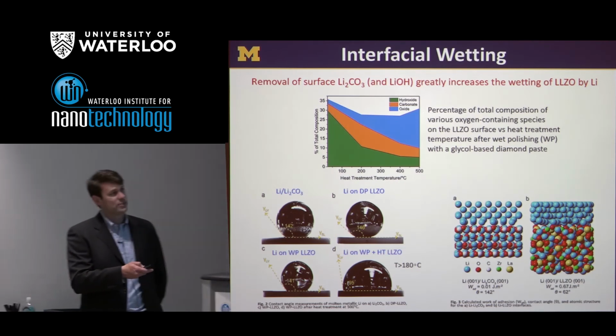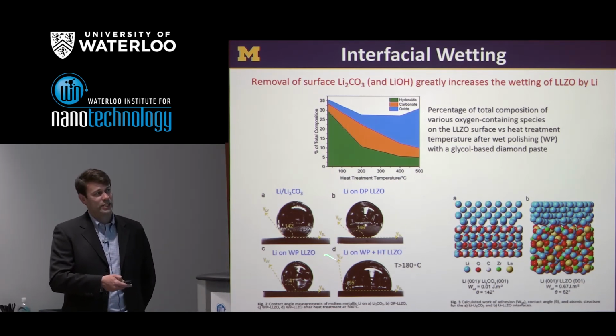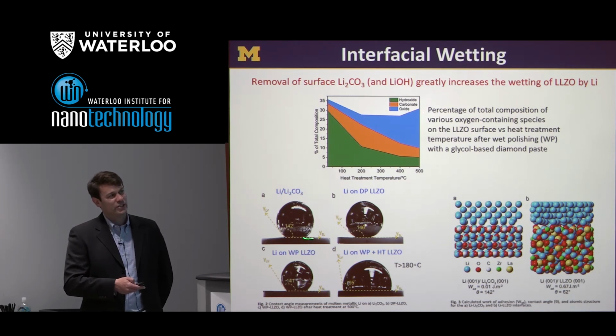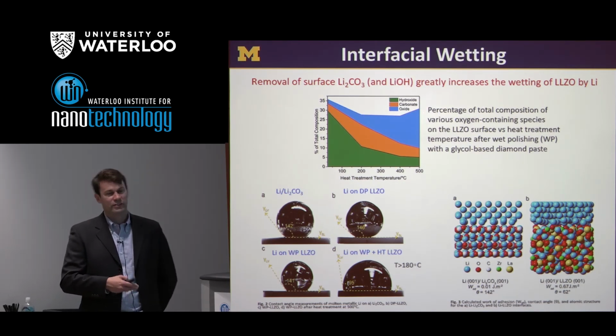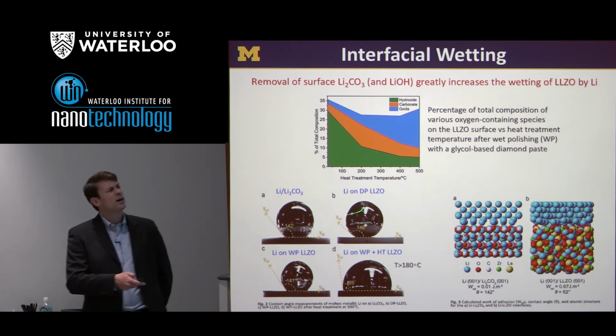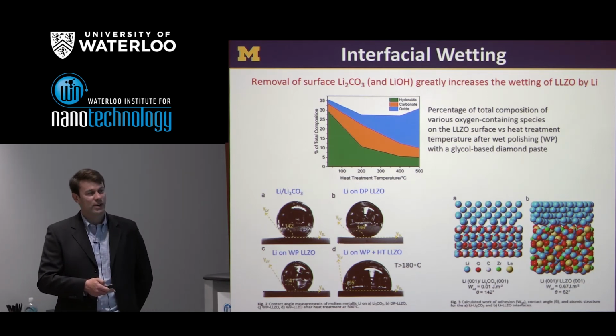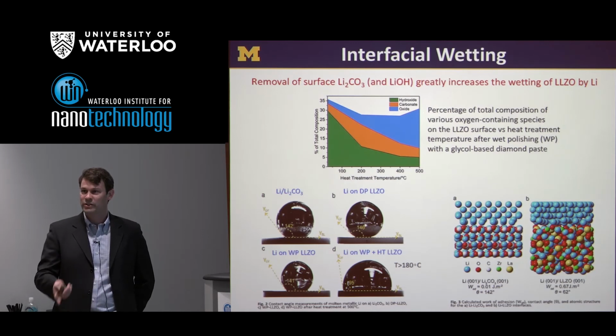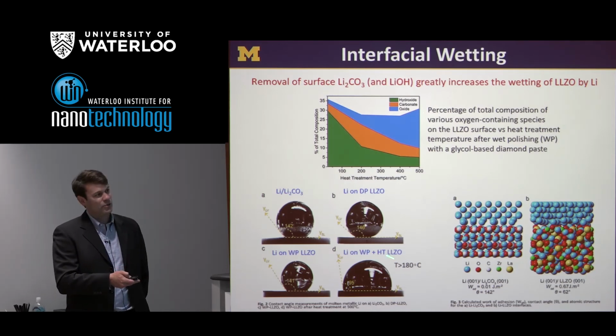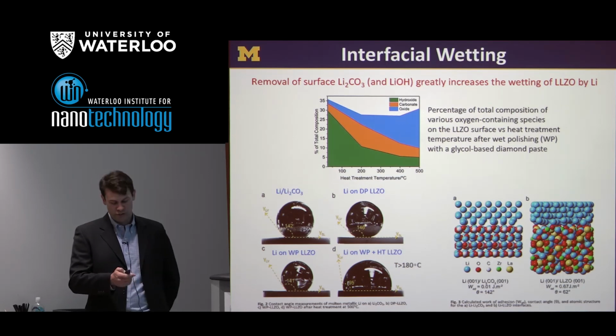And when that happens, there's a dramatic change in the wettability. What I'm showing here are photographs of molten lithium metal on substrates of either lithium carbonate, dry polished LLZO, wet polished LLZO, and then wet polished plus heat treatment. As you can see, for these 3 cases, there's basically very little interaction. A large contact angle like this indicates very weak adhesion between the lithium metal and the substrate. However, when you wet polish and heat treat, this interaction becomes much stronger.